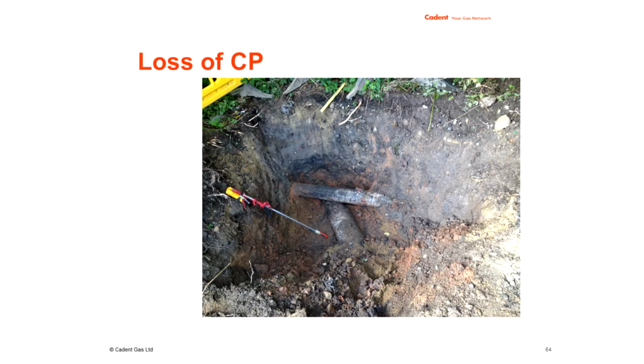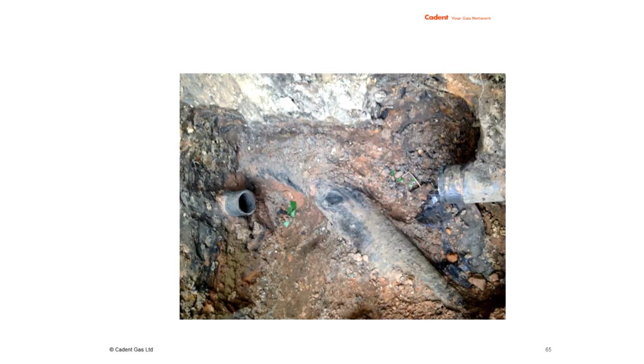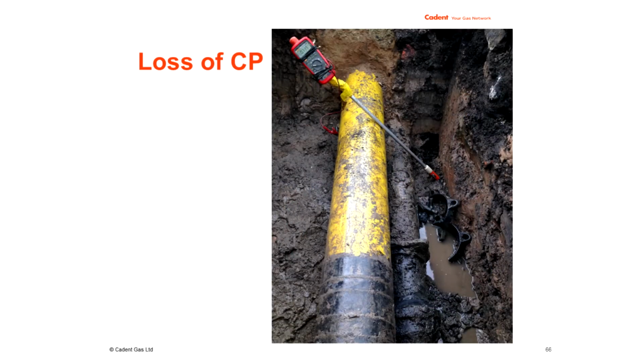That picture there shows a water main, which was a fire hydrant ring main on one of our AGIs, which was laid on top of another one of our steel pipelines. Luckily it was decommissioned so we could cut it out and restore the CP on that site. This one is an ironic situation because the yellow pipe is an intermediate pressure pipeline that was laid on top of a medium pressure cast iron pipeline so that we could decommission the medium pressure one. However, straight away the CP was lost, and it took years to locate the touch points and then smash off the cast iron sections that were in contact.